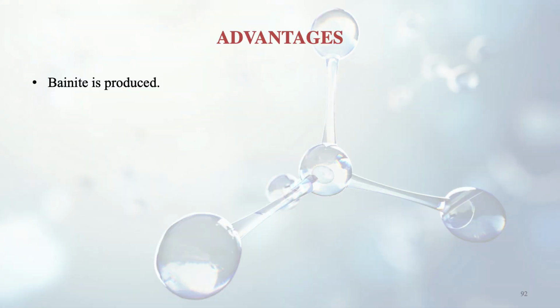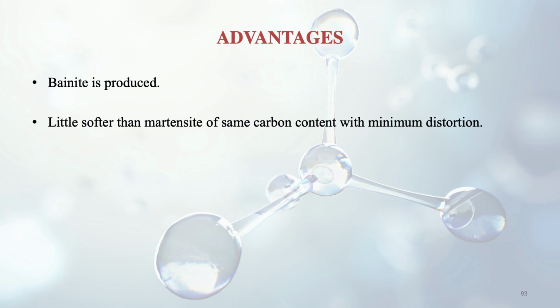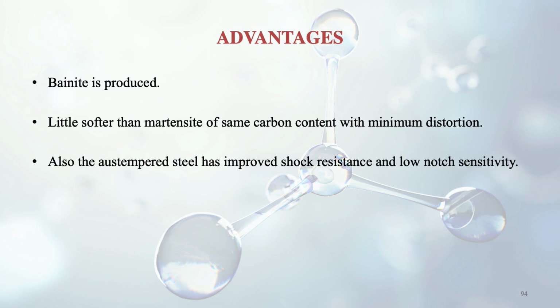So here we are doing the bainite production. The cooling is done in air till room temperature is reached. So this is about austempering. As we have discussed, bainite is produced and it is a little softer than martensite of the same carbon content. That's why we are doing this austempering, and there is minimum distortion. Also, the austempered steel has improved shock resistance and low notch sensitivity. So if we are doing austempering, then we are getting better shock performance. That means it is more shock resistant. Impact resistance also increases, with low notch sensitivity.